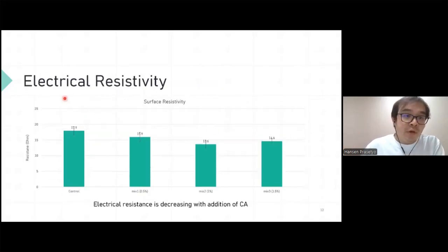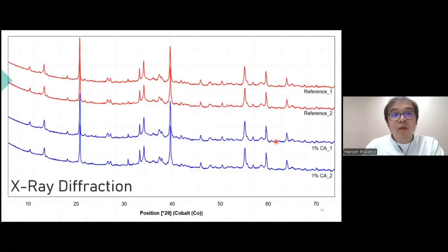And then with the electrical resistivity, here is the first difference that we see. We see that the electrical resistance is decreasing when we add CA into the mix, and yeah, this could mean something, but we'll talk about it at the end.